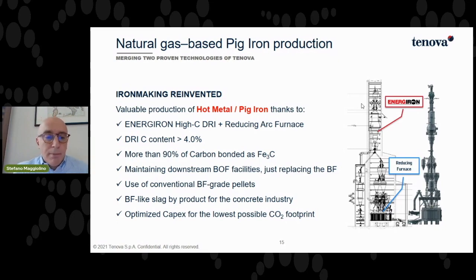With this system, we basically combine a plant that produces DRI with carbon content above 4%, and then we produce hot metal that can be tapped into torpedoes as they actually do now. We basically replace the blast furnace operation, maintaining all the downstream facilities and operation with the BOF exactly as it is now. We have additional advantages.